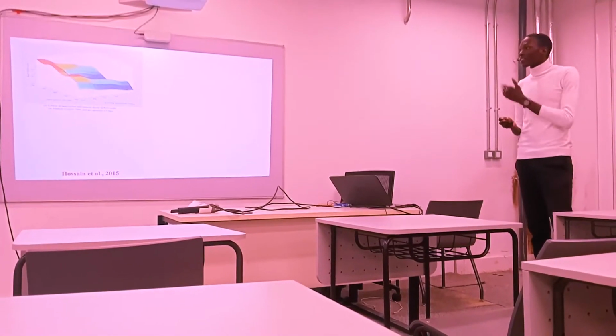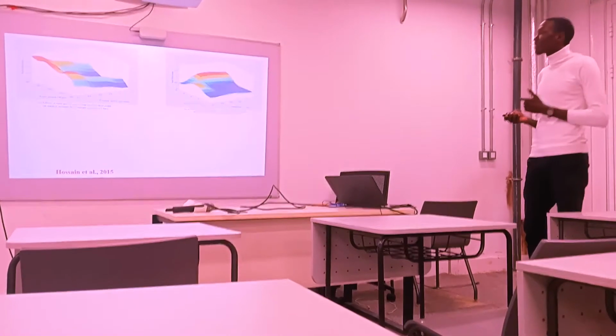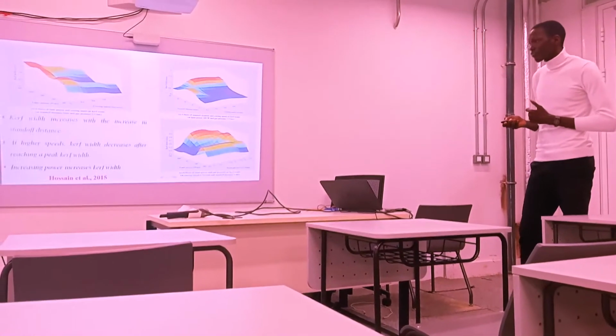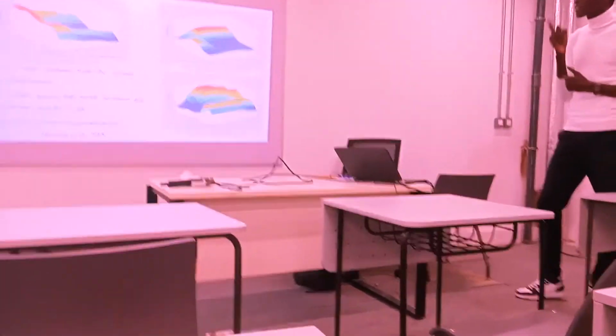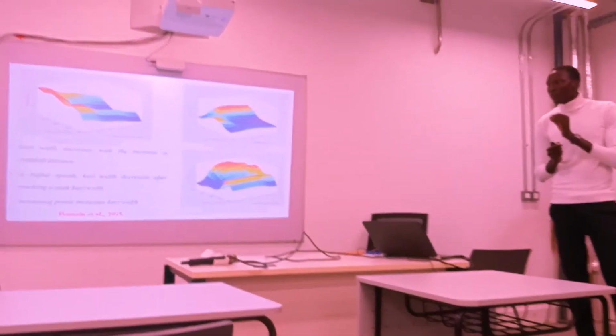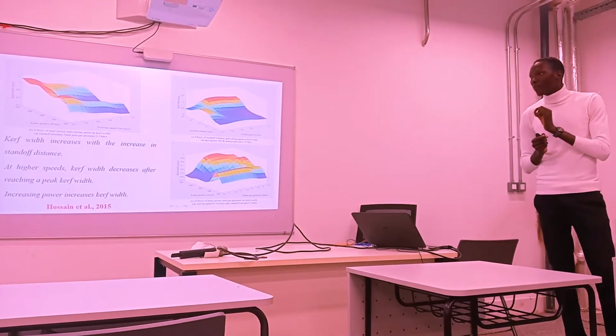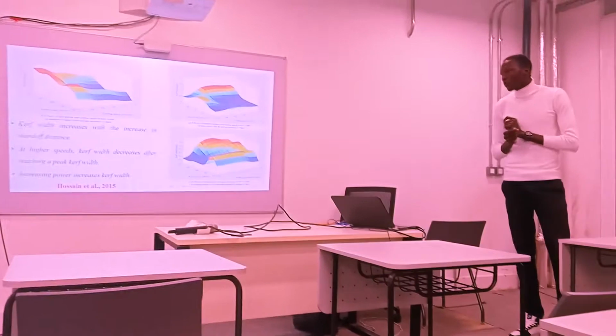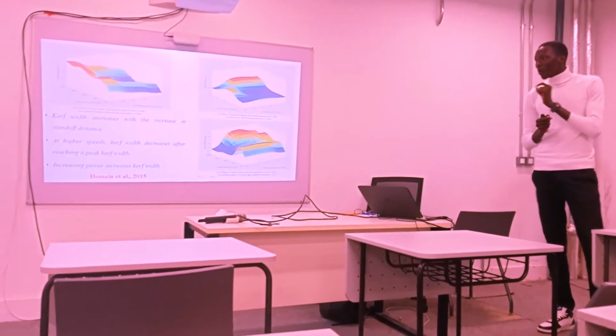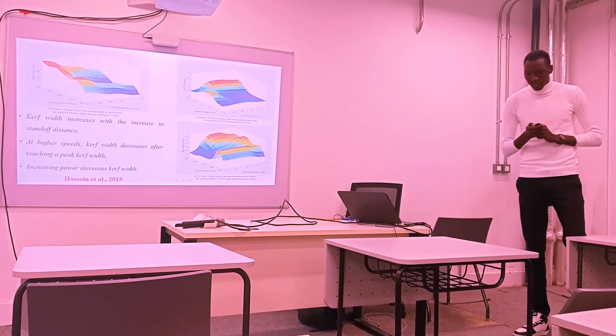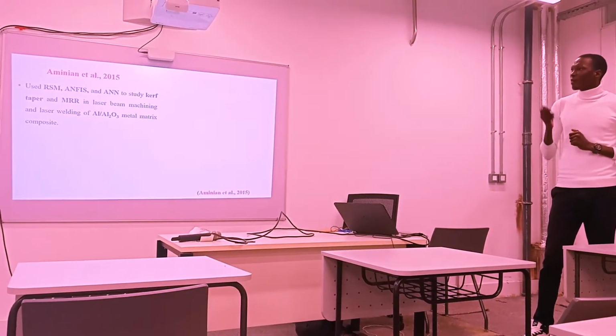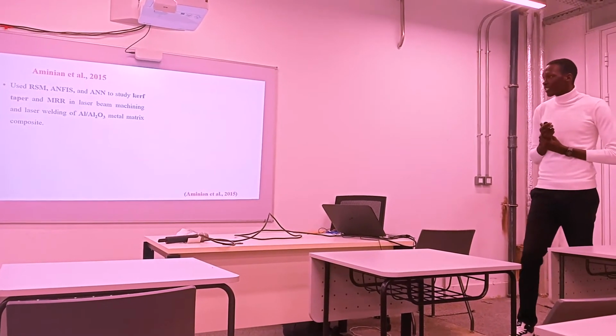Now these are the surface plots that they produced. And they concluded that kerf width increases with the increase in the standoff distance. At higher speeds, kerf width decreases after reaching a peak value. And then increasing power increases the values of the kerf width. Aminian and others in 2015 conducted a very interesting study.